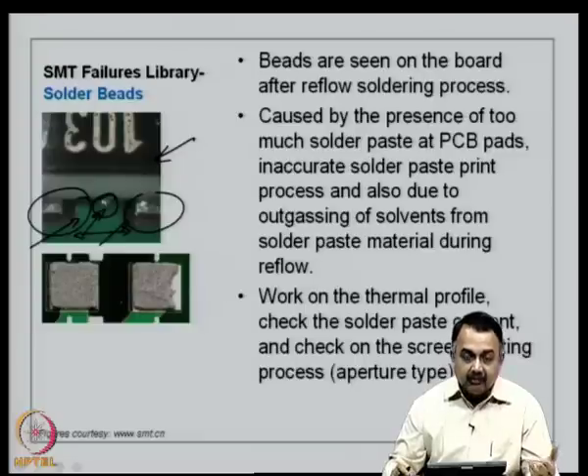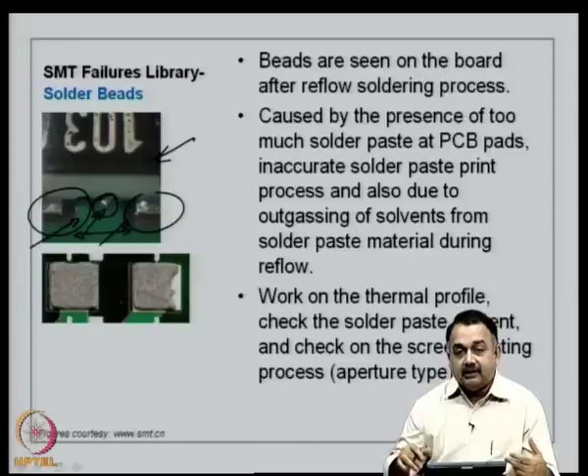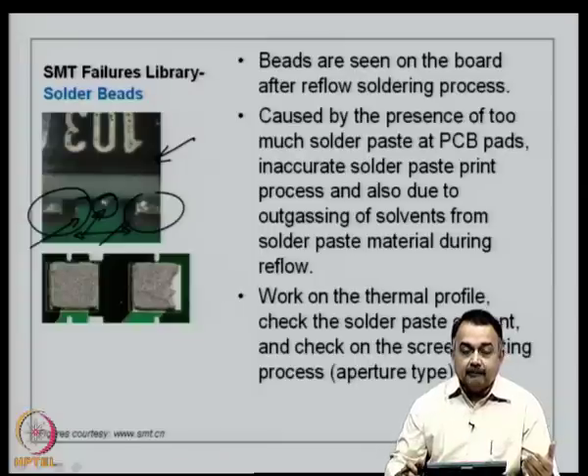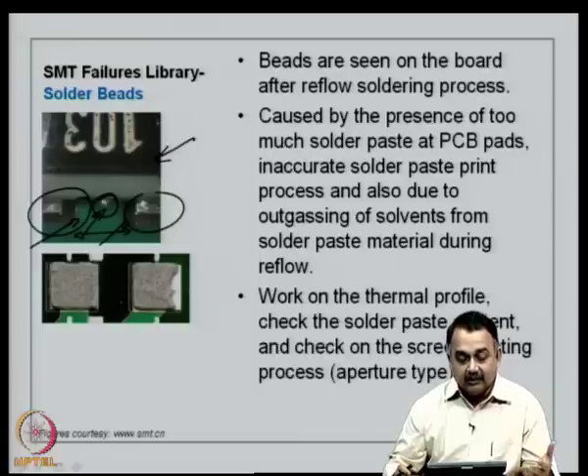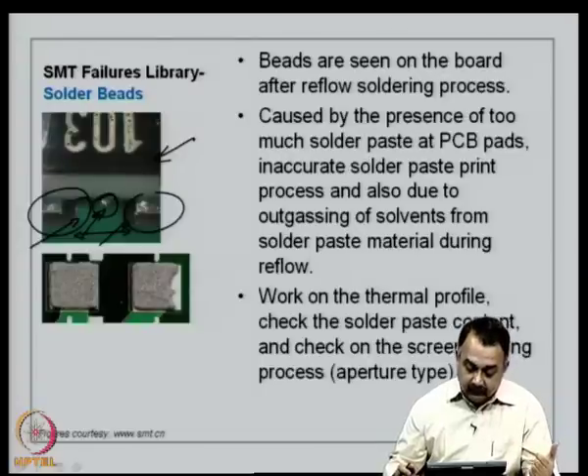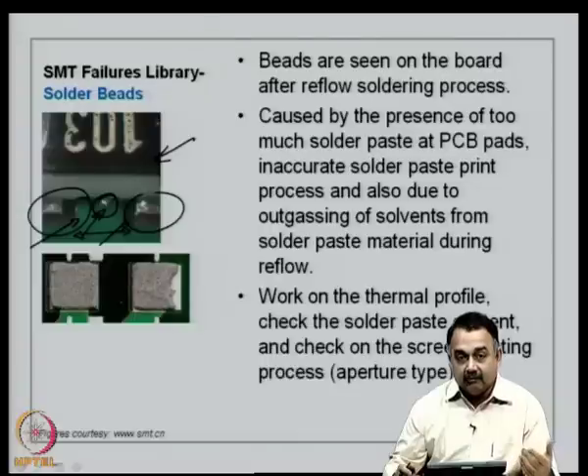So, beads are seen on the board after the reflow process. How has this happened? The solvents in the solder paste have boiled or evaporated, because you have set a thermal profile which is absolutely wrong. You have done a very fast preheating, and then it has outgassed. All the material has sputtered, and during the sputtering process, the solder bead has been thrown out close to the package or under the package or close to a copper pad. Okay. So, outgassing of solvents from the solder paste material due to poor thermal profile during reflow is one of the main reasons for solder bead formation.